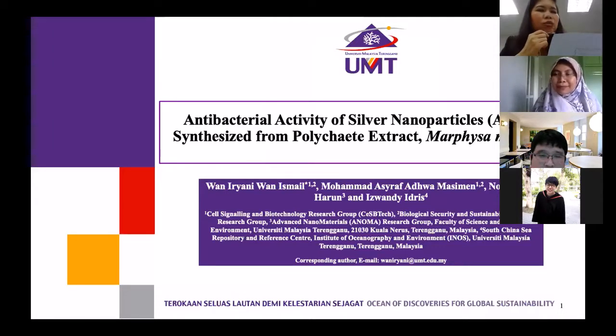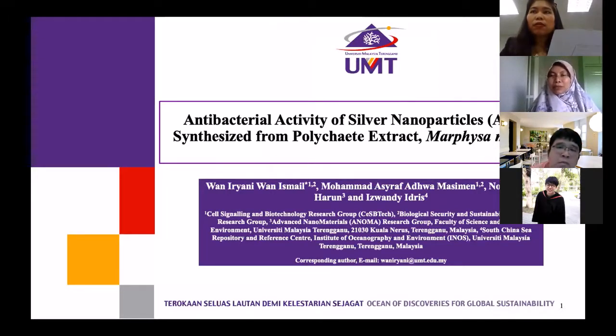Okay. The next one is, in the method of antimicrobial activity, how many time points were tested? Since the results show that at 6 hours, the nanoparticle could inhibit bacterial growth. Yeah, we tested every 2 hours. So 2 hours, 4 hours, 6 hours, up to 24 hours. And then we measured that 6 hours is the best time to kill the bacteria. Thank you.